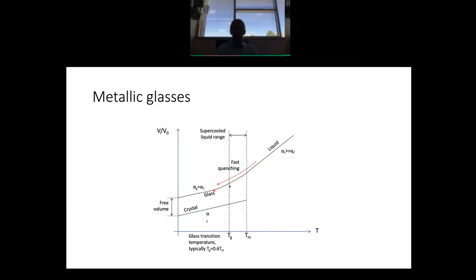Okay, this is something that is very difficult to achieve in single element materials. Most single element materials do not undergo this glass transition, except maybe at extremely fast quench rates. So for instance, silicon will become amorphous silicon if you quench it at extremely fast quench rates. And by extremely fast, I mean like 10 to the 10 per second. And that's the only real example of a single element material that I know that will do this.